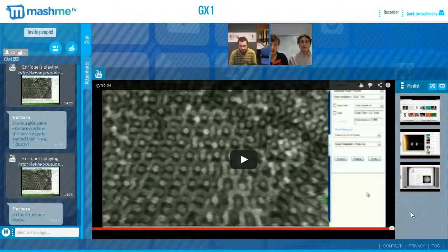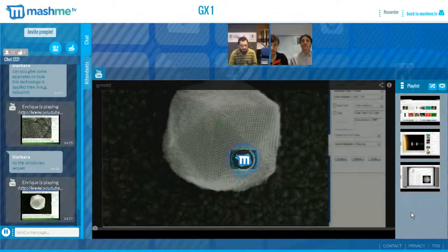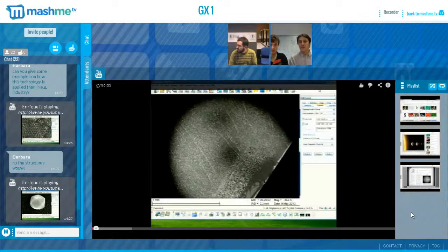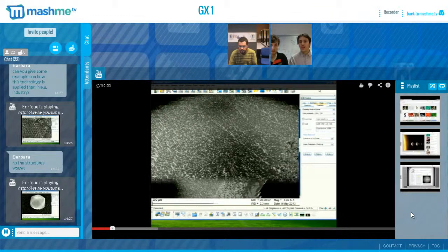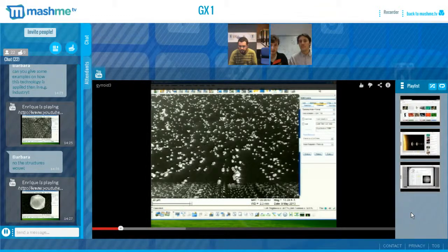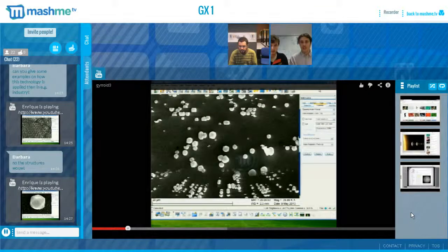Okay, Enrique, can you quickly also load the second gyroid video? Okay. So the video we looked at before is a full film of these gyroid structured materials, while the next video shows a nucleation and growth process. Doing electrochemistry, we only have a low density of nucleation points, and then we get nanoparticles that have an internal gyroid structure.